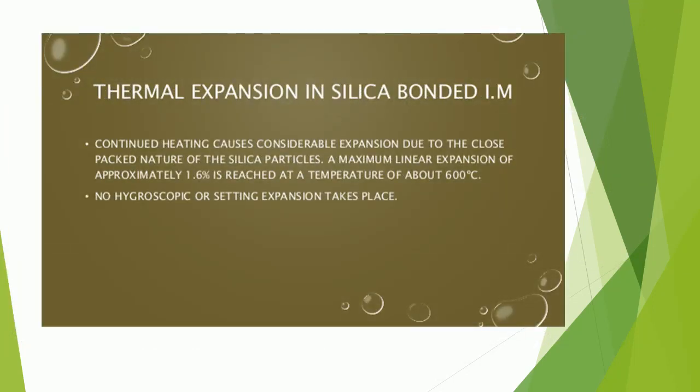Thermal expansion also takes place in the silica bonded investment material. The continued heating, as we gradually increase the temperature, causes the expansion due to the close packed nature of the silica particles. And it is observed that almost an expansion of 1.6% is reached at a temperature of 600 degrees Celsius. However, it is important to note that there is no hygroscopic or setting expansion in silica bonded investment materials. The only expansion that takes place is thermal expansion and some crystalline inversion due to the presence of silica.